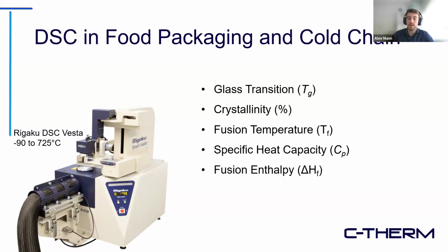Next, we have crystallinity. This is important because it gives an insight into transparency versus opacity, as well as flexibility and impact resistance. The fusion temperatures are also really important for determining the upper limits of the plastics or your insulation and whatnot. For example, you don't want to take stuff near the melting point because then it gets really soft, becomes a liquid, loses shape. Especially if you're taking food and you store it somewhere, like a hot soup, you don't want to melt your container. And lastly, the specific heat capacity and the enthalpy of fusion are especially useful for thermal management, especially in phase change materials, which Arya touched on a little bit.